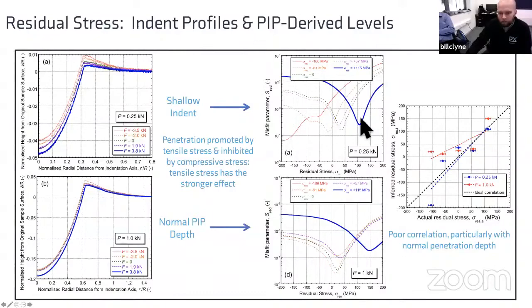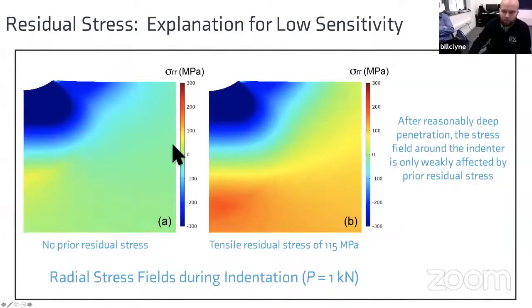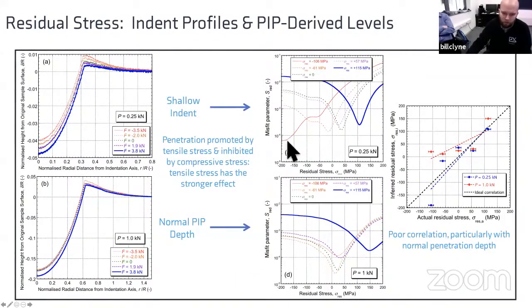And we can see that the correlation at the lower depth is okay. So here, the blue one is actually a residual stress of 115 megapascals. That's quite close. It's a bit less well defined in this region, but as we go negative, we have -60 and -30 and -106. My apologies, -106 would actually, we're predicting residual stress of almost -200 there. And then we can see for the deeper indents, we're getting much less sensitivity to the residual stress. So as we might have expected, looking at those indentation profiles, there is very little sensitivity at those depths.